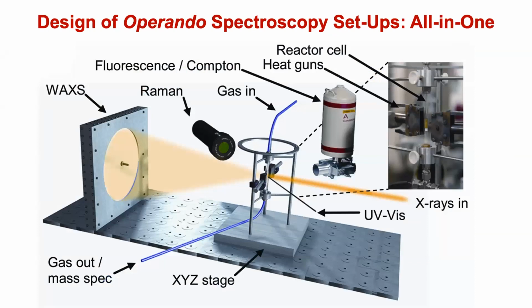One of the systems we have been developing about 10 years ago, and I think that is something you see now also at synchrotrons, is a very complex system where you combine techniques. On the top right you see a reactor with an orange powder, a catalyst. You see the heater guns. Now this is a very interesting one. So you have heating guns around a reactor, a capillary, and you have a lot of space. A lot of space is good because it means you can start to put a lot of techniques, which can be wide angle X-ray scattering, X-ray diffraction, you name it.